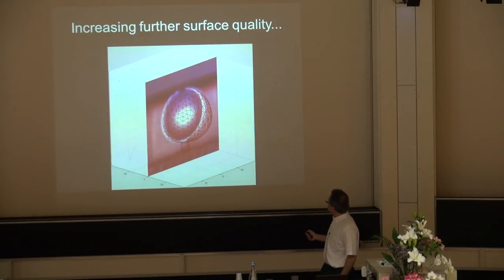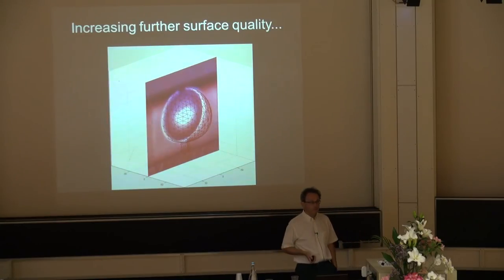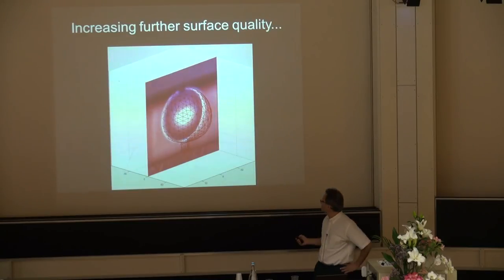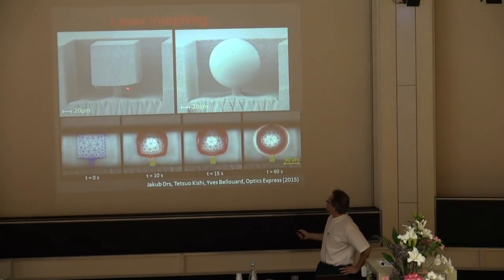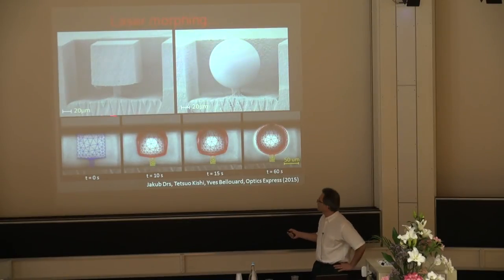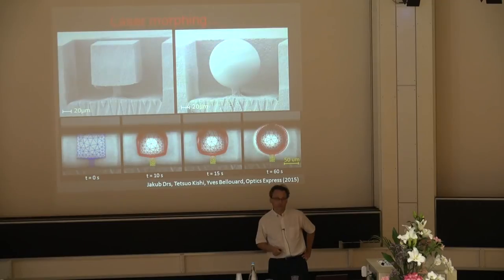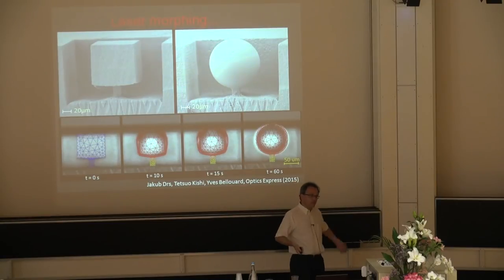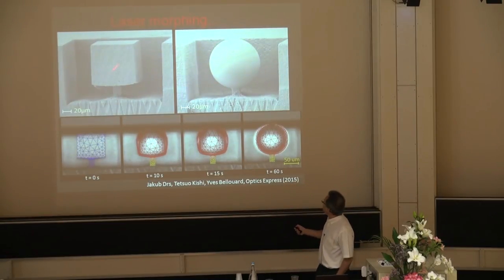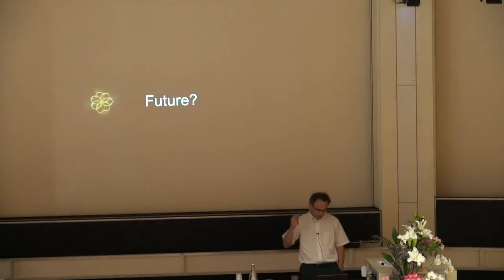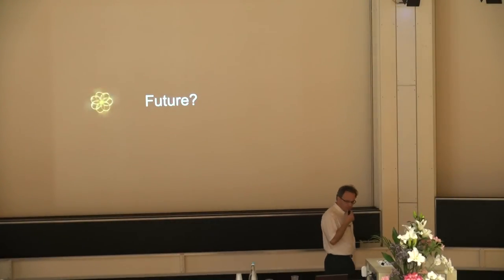And you can already see that this has nice optical properties, because the light is a bit trapped in there, and you see this halo of light around. So you can imagine this is particularly interesting for resonators. Here you see the first shape to start with is not bad, actually. If you look at the roughness here, it's already comparable to EDM, for instance, but of course it's not perfect. Now, if I fire the laser on that, this will turn into a perfect sphere, and you see these evolutions here. Now, I've shown you just a few examples, but there are many things we could talk about.